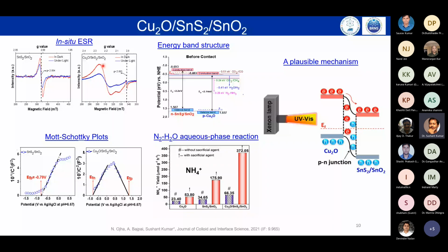to diamagnetic Cu+. And then we did Mott-Schottky plots to see the effect of using p-type and n-type semiconductors. Here you see this is an n-type, and this is a p-type and n-type. When we have this kind of heterostructure, we were keen to understand how this kind of photocatalyst works. Here you can see the energy band structure, starting from the valence band to the conduction band. Here the conduction band is of p type, and this is the n type. These were the potentials for the CO2 to CO conversion: minus 0.693 for SnS2 and SnO2, and for Cu2O we have minus 0.483.